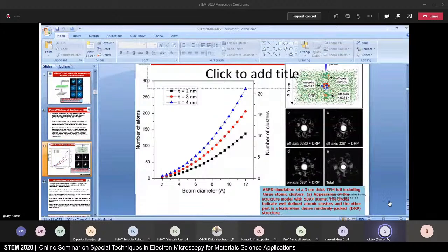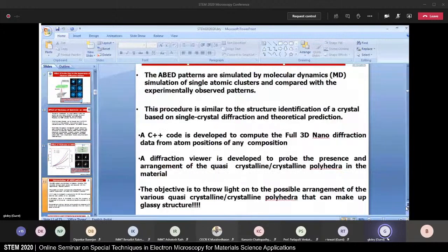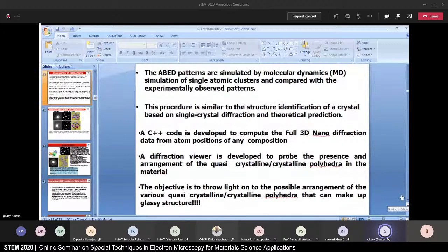So how do you interpret the diffraction pattern? The diffraction pattern is interpreted in this case exactly the same way as it is done in case of crystalline material. Namely, you simulate the diffraction pattern using molecular dynamic simulations, and you get a simulated diffraction pattern, match it with the observed pattern, and if they are in agreement, then whatever structure you have simulated is the actual structure